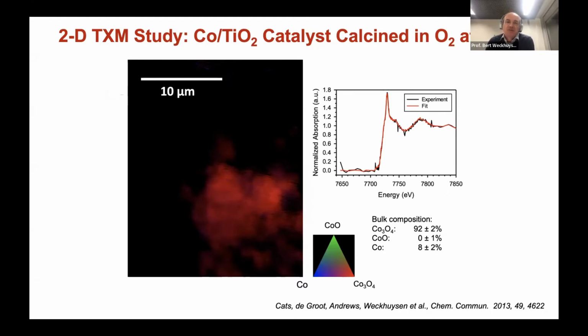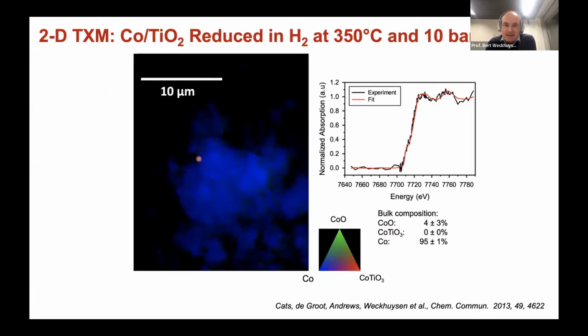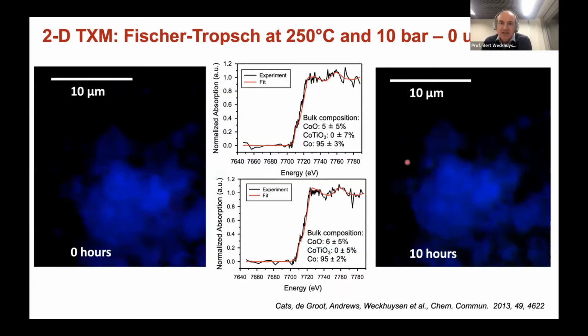I will come back now to the catalyst which I want to discuss in detail, which is the cobalt titanium. Here I show you a 2D image. This is the spectrum. We can determine with different compounds what it is. Actually, it's cobalt oxide. Then you bring it in hydrogen, you reduce it. Spectrum changes. I have to admit, it is noisy, but you have already seen this tiny capillary. So I hope you're also convinced this is a challenge to do this. But we succeeded, and we can measure further.